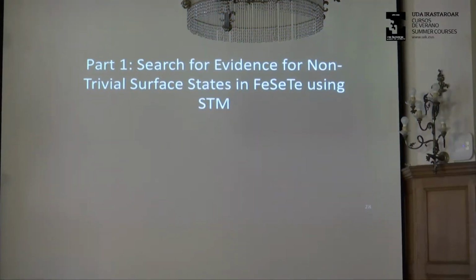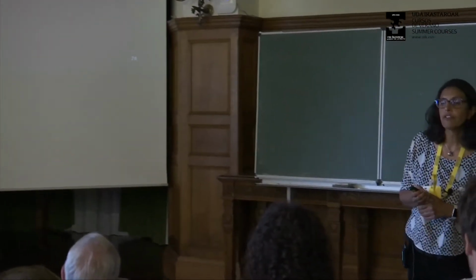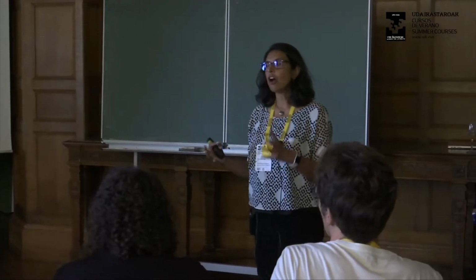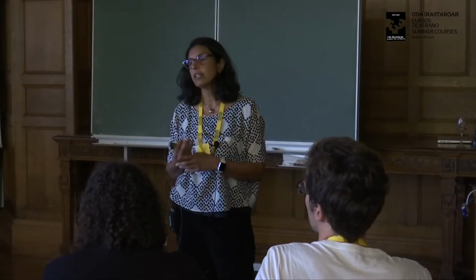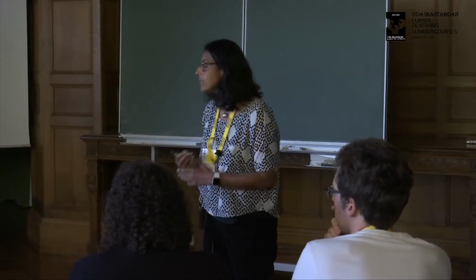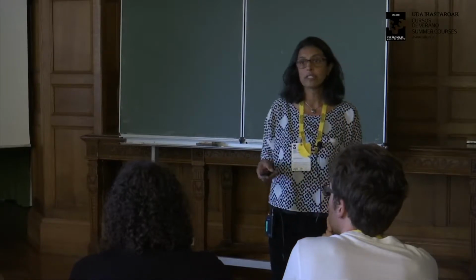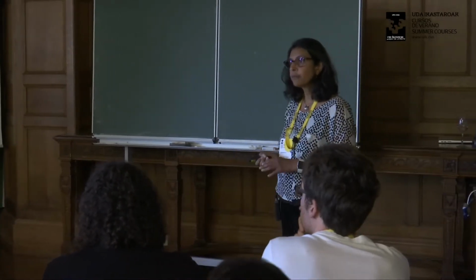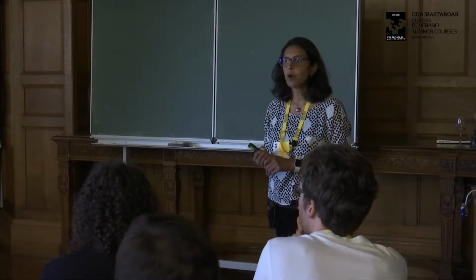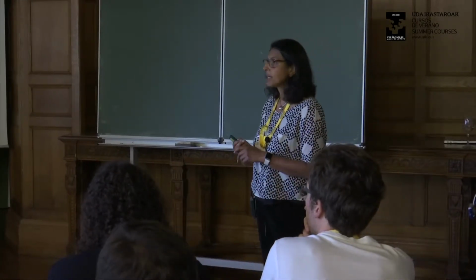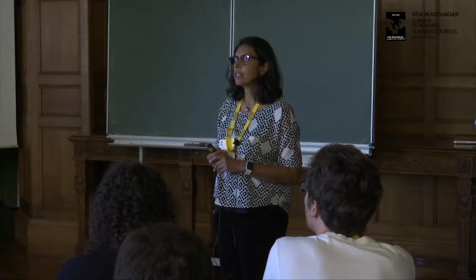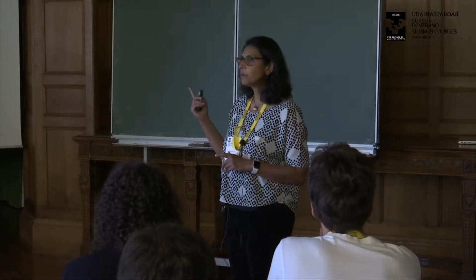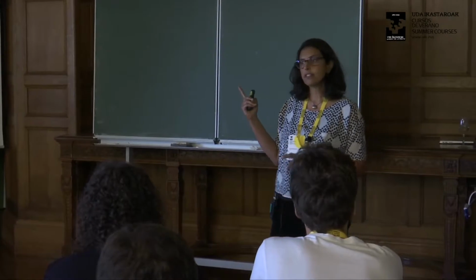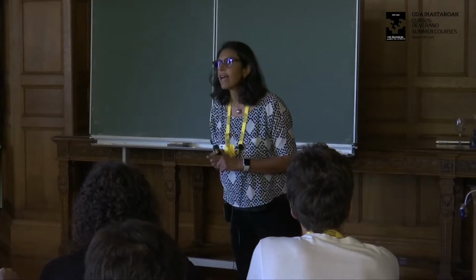So the first question we wanted to ask, when these results first came out, we were very curious because there was a lot of controversy about this material. Is it topologically non-trivial? Do we really have surface states? So the first question we were trying to answer is, is there any evidence for these non-trivial surface states in STM? Now, I'll show you tomorrow, you can often use more complex techniques like quasiparticle interference and Landau level spectroscopy to look at non-trivial surface states. But QPI can't be used for Dirac surface states near the Dirac cone because backscattering is forbidden.